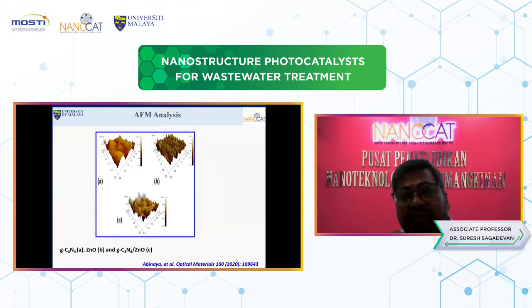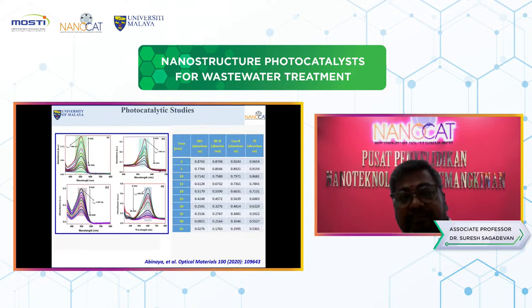Again, we can confirm that from the topographical image, for the roughness of these composite materials. We can look at the sheet-like morphology for A, graphitic carbon nitride, and rod-like shape morphology for B, zinc oxide, and C shows how the zinc oxide is incorporated with the graphene sheet. That is clear evidence in the topographic image of AFM analysis, once again confirming the successful formation of this composite.